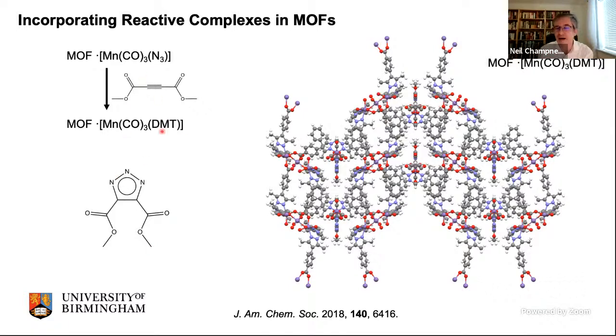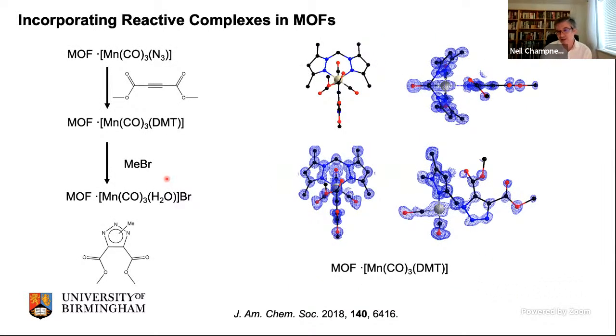So we diffuse in an alkyne. An activating alkyne works better. It diffuses in, and you can see from this crystal structure that the alkyne is reacting with the azide. I'll show you a better picture in a second. And it's making this triazole, and this is akin to click reactions that you see in the literature. So here you can see it from the other side. This is looking at the electron density. This is how you tell from a crystal structure what's going on. Here you can see the triazole species bound to the manganese center, and this is determined crystallographically. So we can actually see the different steps in a reaction sequence, and in fact we can even liberate the triazole by alkylating it with methyl bromide and generating the bromide complex again.